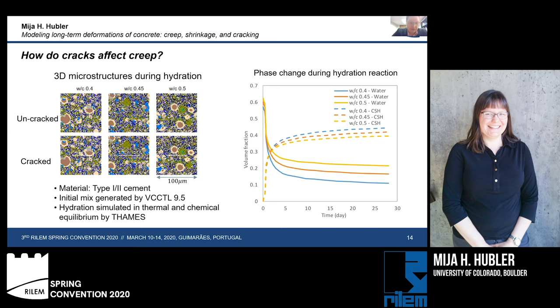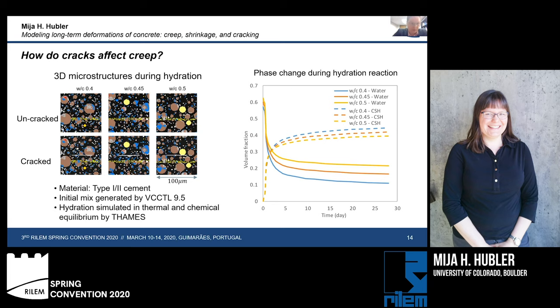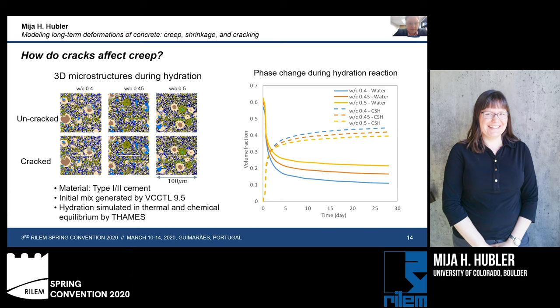So here we have a numerical model of the hydration process of an uncracked and a cracked piece of cement that's 100 micrometers for different water to cement ratios. We're considering a type 1-2 type of cement, and the initial mix is generated from image data using the VCCTL software. The hydration is simulated in thermal and chemical equilibrium using the THAMES software.